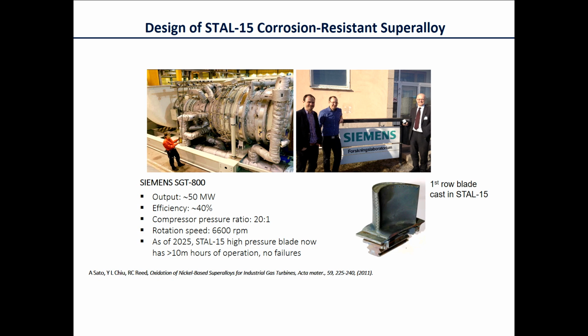these single crystal materials tend to corrode very rapidly at high temperatures. So the temperature of the hot gas may be as high as maybe 1500 Kelvin, maybe even up to 2000 Kelvin in some advanced aero engines. And so there's a risk, of course, that the blades here will corrode over time.